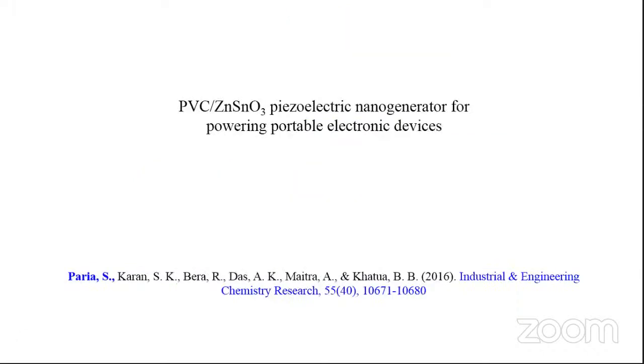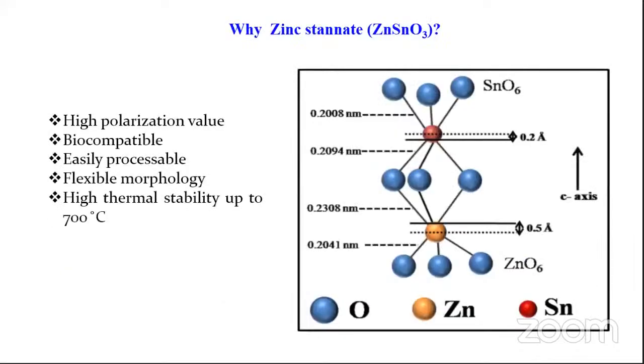So in our first work, we have used a PVC and zinc stannate based piezoelectric nanogenerator. Here we have used PVC because it is very good in flame retardant properties, and zinc stannate is an emerging nanoparticle. So why have we used zinc stannate nanoparticle? If you have seen here, it has a high polarization value. From where does it show a high polarization value?